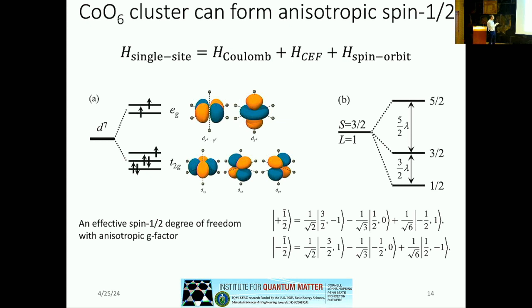But the t2g level has a triplet orbital, a threefold orbital degeneracy, which can be described as a pseudo spin one orbital degree of freedom. So you have a spin three half and an orbital angular momentum one, and they get coupled by spin-orbit interactions, which will split this otherwise 12-fold degeneracy and select in the lowest energy regime the spin one half type degree of freedom. The splitting from the doublet to the quartet is on the order of 40 to 50 millielectron volts, so it's a fairly high energy scale, typically much higher than the exchange interaction. So we can think of everything as just happening in this spin-orbital doublet state. This really is an effective spin one half degree of freedom, but it carries an orbital angular momentum, and therefore it has a very anisotropic g factor.